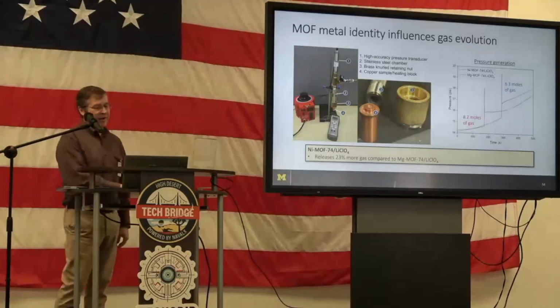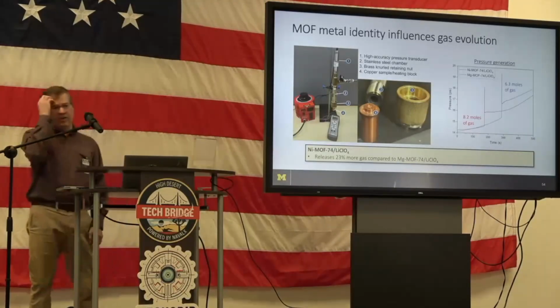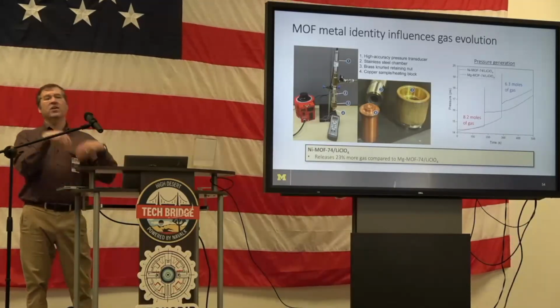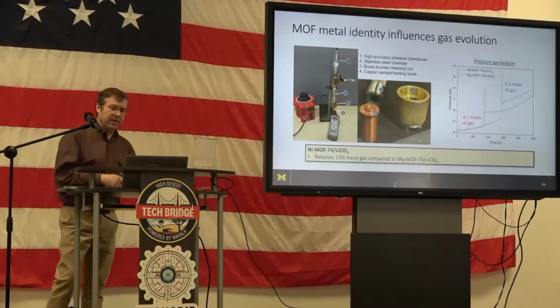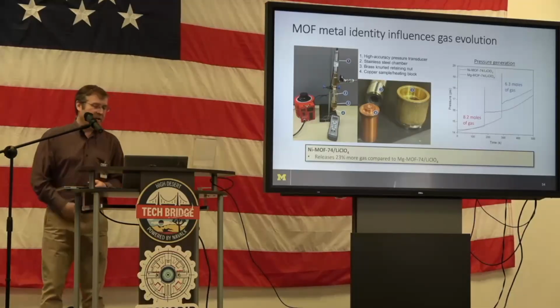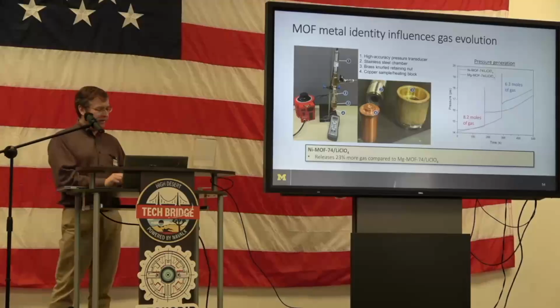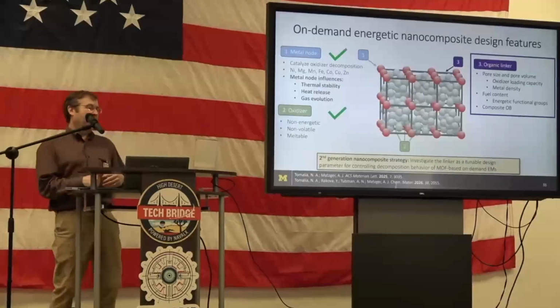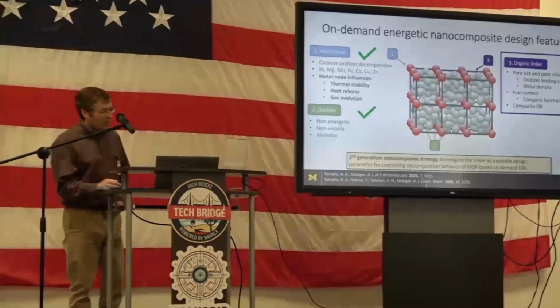We find that we're getting more gas evolution in the presence of the nickel catalyst than the magnesium as a structural metal. And so we've done that. We've published on that. Now, what's much more recent, we just published, I think, this year, is changing the organic linker. So the organic linker is the source of our fuel, but not just the source of our fuel.